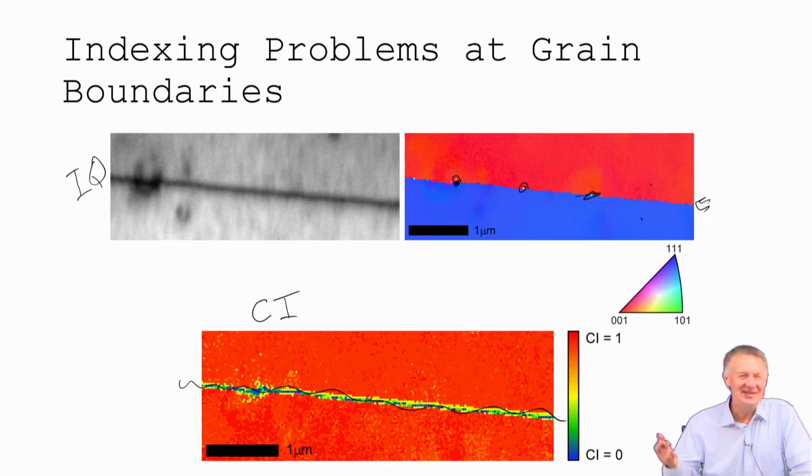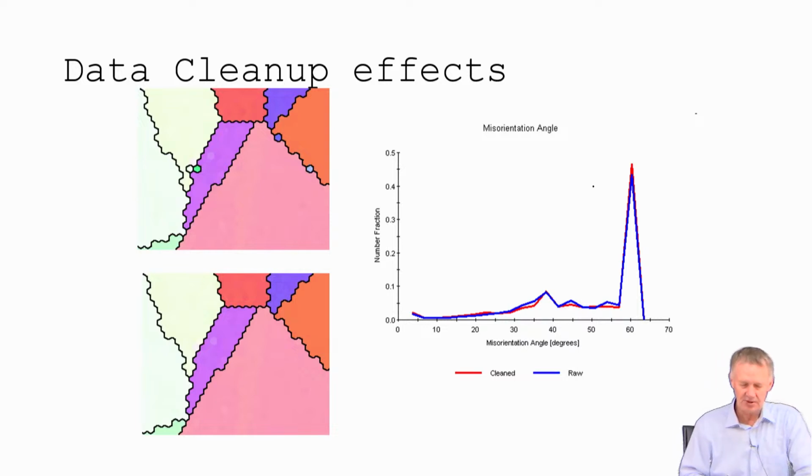Anyway, so now I'm cleaning those up, right? So I tell my students, never clean up, never clean up, never clean up. Sometimes clean up. If it's for specific boundary statistics, I would clean up; for texture, I would never clean up, right? Because then I'm creating new data. For this, I'm just plugging the holes on the boundary, but I still have to tell the computer what's true, right? So here's another example.